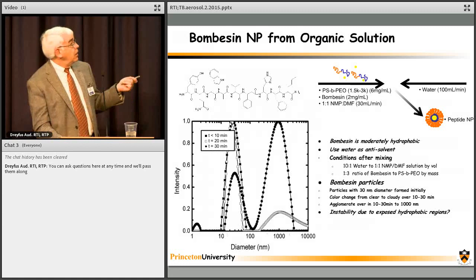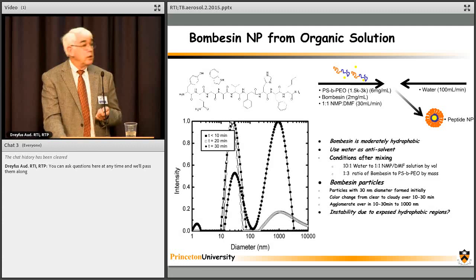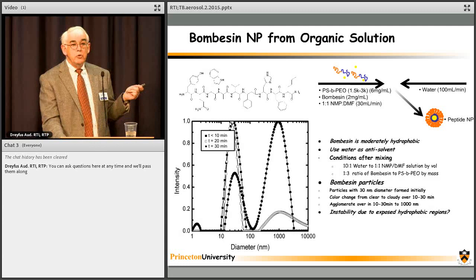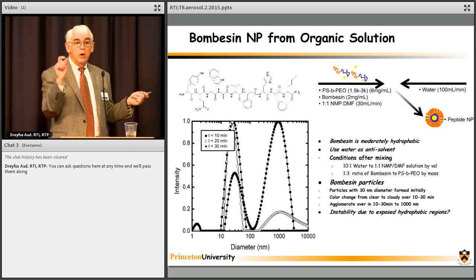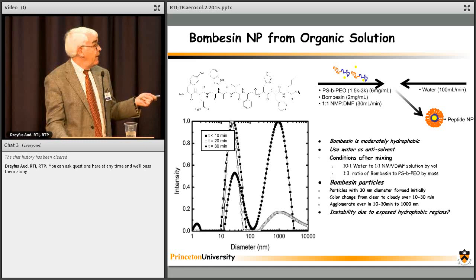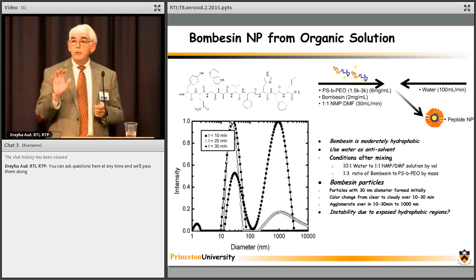And one of the other peptides is called bombesin. It's a natural product, again used in a commercial therapeutic application. And what happened here was really interesting. So you do the initial precipitation, and what you see is 30 nanometer nanoparticles that are formed. You do this and do the light scattering immediately, and you see you have 30 nanometer things. And then over time, at 20 minutes and 30 minutes, this peak goes down and that peak goes up at about a micron. So it's unstable, but it's unstable in a very specific way.